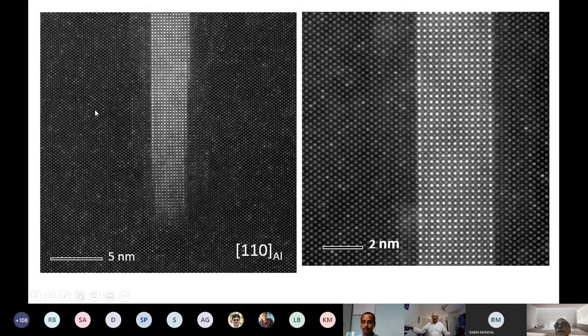Inside it is copper, but at the edge, at the interface, it is hafnium, and it is so uniformly distributed and segregated that it cannot grow. It can grow only by step. So you can see, as it tries to grow, it produces a step here, it produces a step here. So only step growth is possible because diffusion is very sluggish. Continuous diffusion growth is not possible. And that is why it is stable, that is why it is strong, and that is why you get high strength. So this is work in progress.